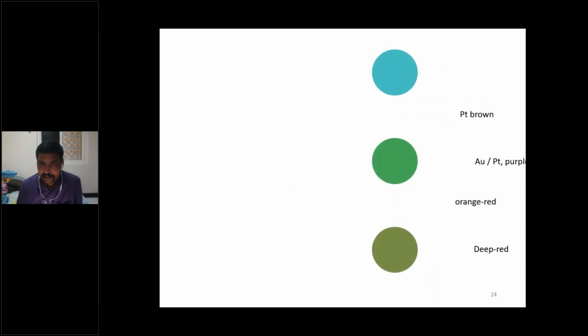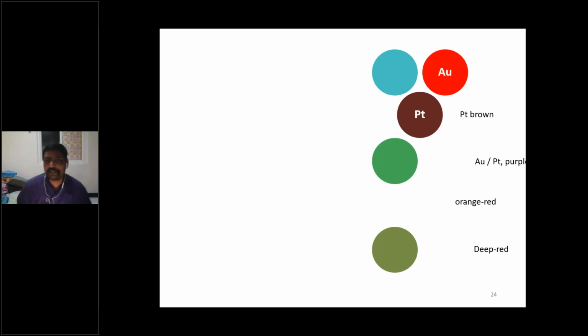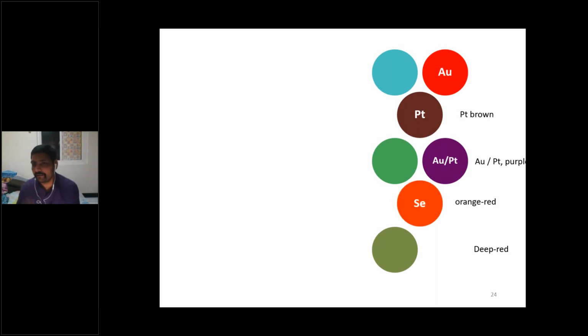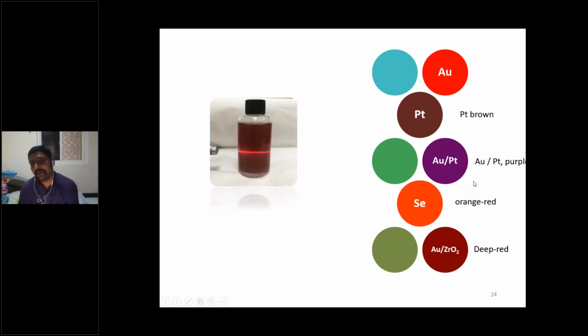The first thing is we are developing a greater number of nanoparticles to give better results with high sensitivity and a low detection amount of antigens and antibodies, and to give various colors to easily differentiate between the test line and the control line. In this case, we have developed gold nanoparticle, platinum nanoparticle, platinum with gold, selenium nanoparticle, and gold with zirconium oxide.